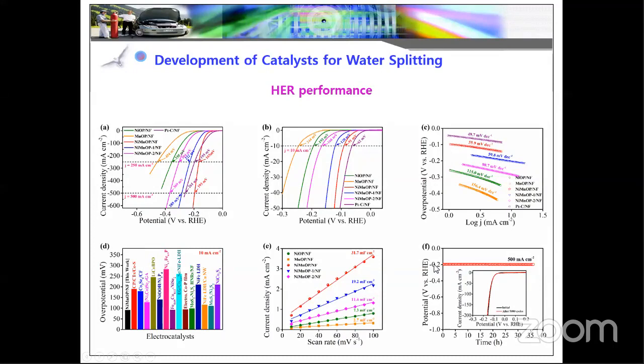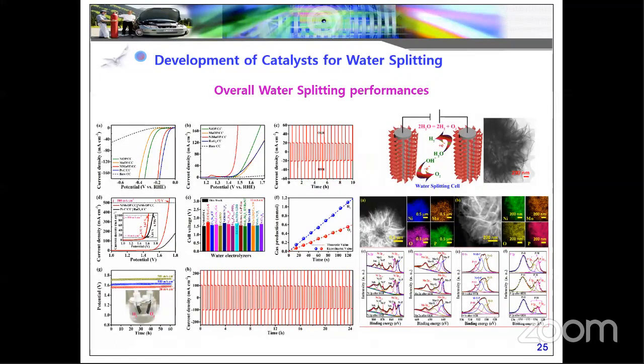You can see this is the negative window, because OER is the positive window. The stability is almost stable around 36 hours. This further confirms our material is highly stable in the aqueous alkaline media and highly active towards HER activity. After HER and OER, we want to go to the bifunctional activity, because we already confirmed it in the 3 electrode system, and we are fabricating the device.